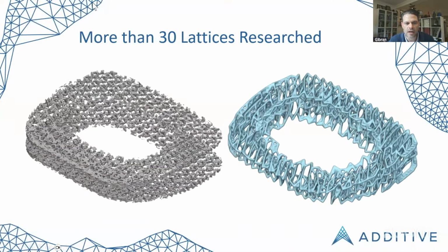What we ended up landing on after going through more than 30 lattices was these two lattice structures here. So the lattice on the left is called a perforated TPMS. It's very sort of grippy, right? It feels like Velcro, the hook and eye loop connector. So we sort of look at that as Velcro for the end plates. So that lattice contacts the end plates of the vertebral bodies. And then in the middle of that Velcro for the end plates, we've got the blue lattice on the right. And that blue lattice on the right is orthofoam. So that's structured very much like trabecular bone. It's got an irregularity in its pore size and it's fully communicating. There's no dead ends, right? So blood can keep going through the entire implant. It doesn't come to a dead end and create a dead space and a potential haven for infection. It is fully communicating.